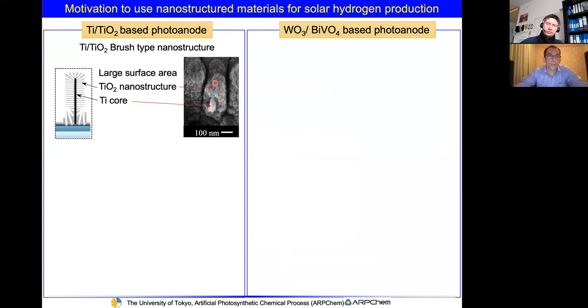Of course, this material has a large surface area, and the photocatalytic working principle is shown here. When the light is irradiated, we can produce pairs of holes and electrons. The holes are extracted to oxidize water, and the electrons come to the very conductive core, reach the conductive substrate, and then hydrogen production can be realized on the platinum counter electrode.